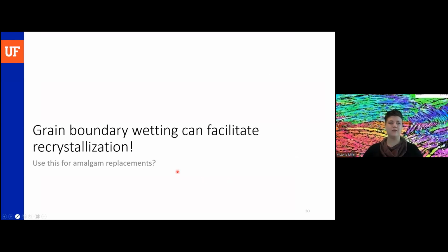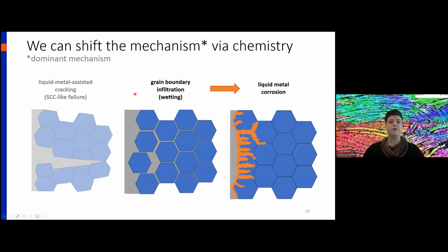The main takeaway, though, is that grain boundary wetting can facilitate recrystallization. So you might be able to use this for, say, amalgam replacements for dental work or other places that you use mercury amalgams. Now, the last part of this that I want to show is that we can shift the mechanism of liquid metal embrittlement via chemistry. And when I say the mechanism, I mean the dominant mechanism.